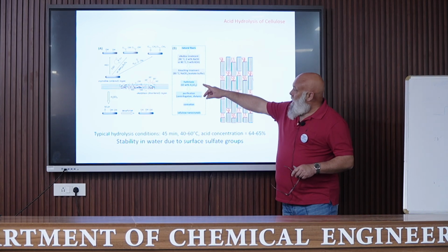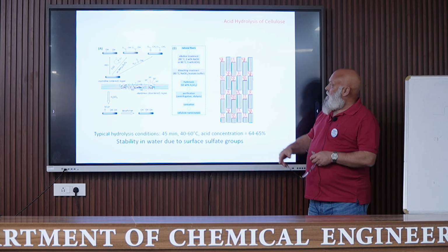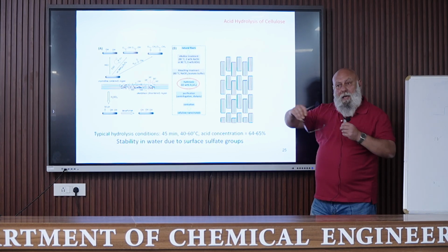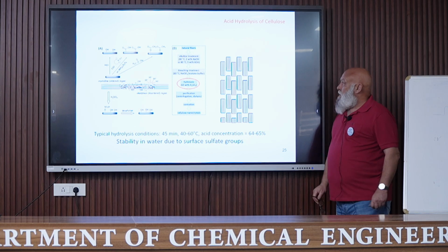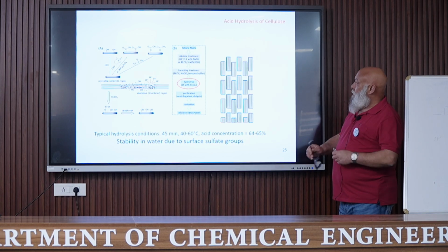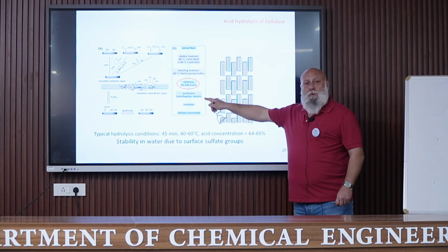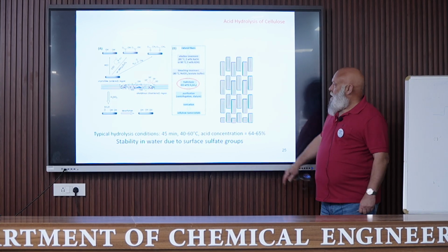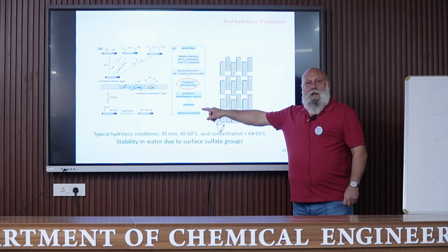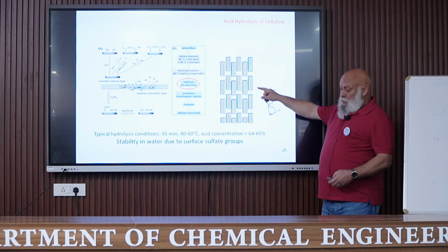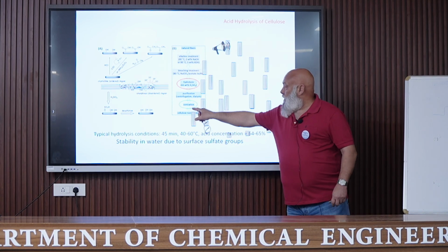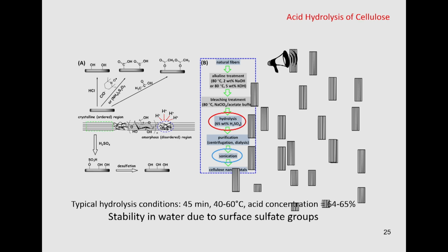And then, after this acid hydrolysis, which removes the amorphous domains that link the crystals in the fiber, a purification step is used just to remove the free acid. A mechanical treatment, sonication, is applied to separate these nanocrystals, and so these nanoparticles are then obtained.